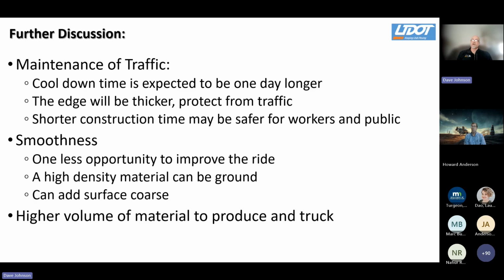There's plenty of information about these more mainline projects, and what Utah has done is lay this material down, profile it, and then do smoothness grinding, bump grinding, if you will, to get to the required smoothness. We'll also see in a slide here in just a moment that this high density material, its grinding operations go very, very well, quite similar to what you might see on a concrete pavement, actually.